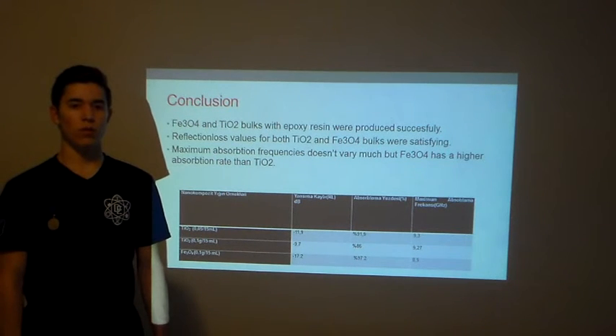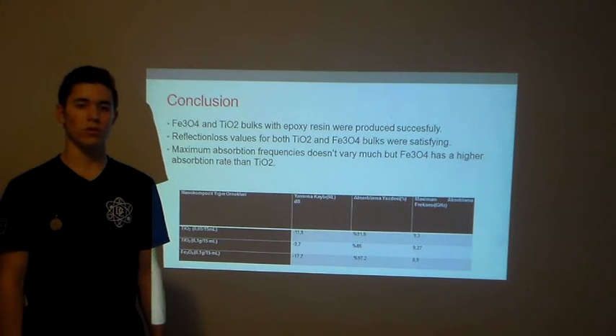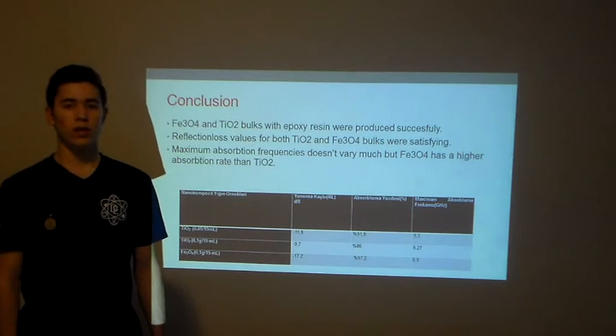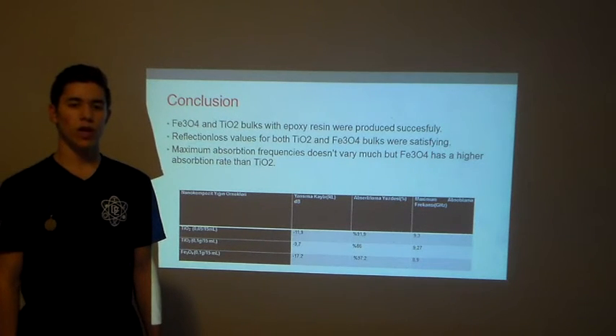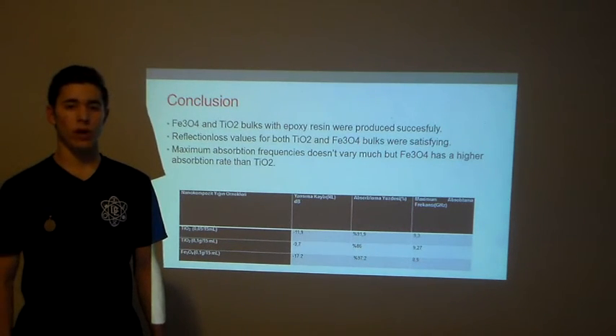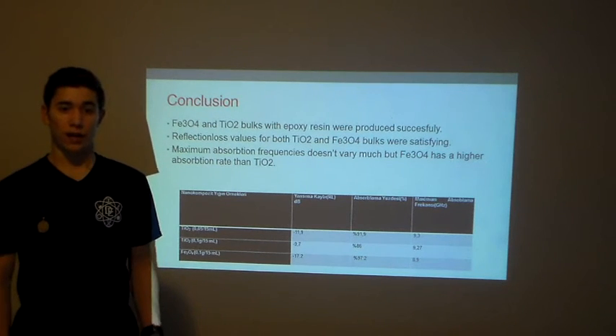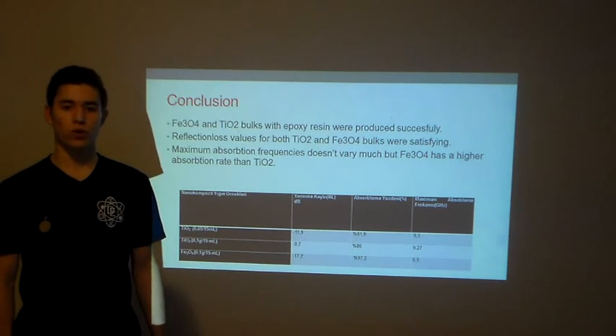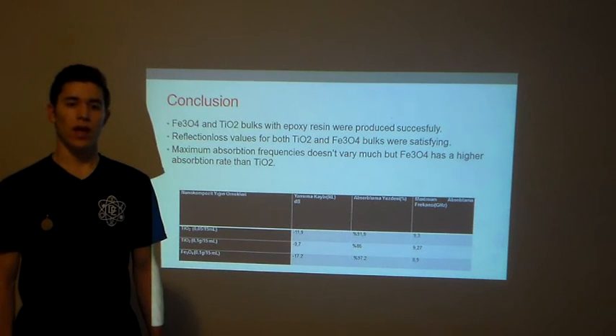Iron oxide has an absorbance rate of nearly 97% and titanium oxide with lower concentration has an absorbance of nearly 92%. Titanium oxide is a diamagnetic material and the reflection loss value increases as concentration decreases. So a good value can be obtained with less titanium oxide. With this, the radar absorbing material on the cover will weigh less. Fuel economy and flight time are among the most important features of a plane, and as it weighs less, those will increase.